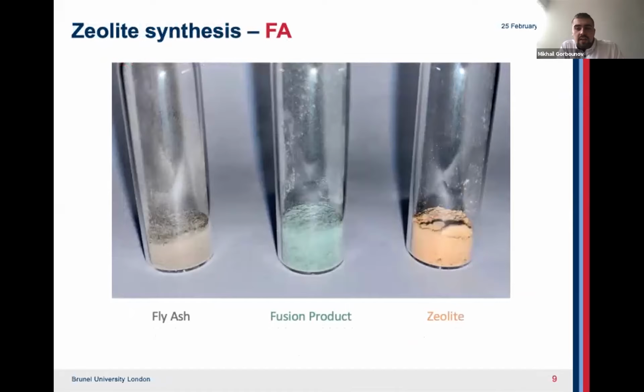Having extensively characterized the fly ash, our research group has looked into the applications of this material for direct carbonation. Unfortunately, the results were not as promising as would have been desired. We have then tried combining the fly ash with various additives, and this approach did yield a more positive outcome. However, it was not economically viable on an industrial scale. Therefore, our next step is to look into zeolite synthesis as a means to valorize this waste.